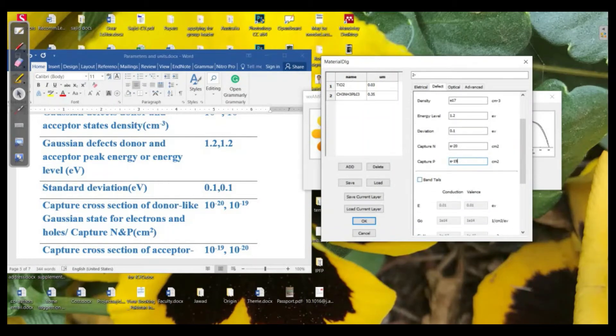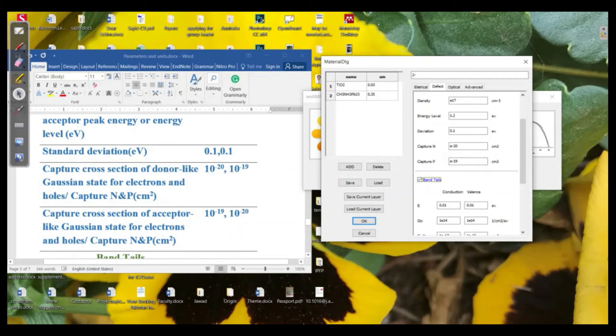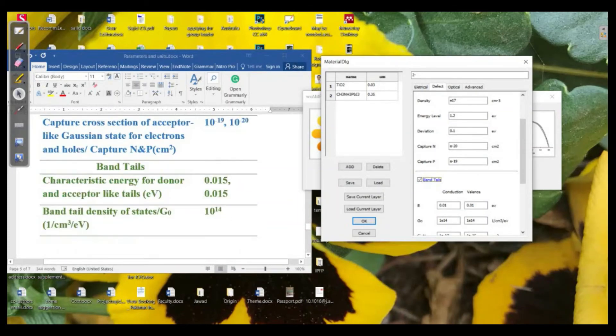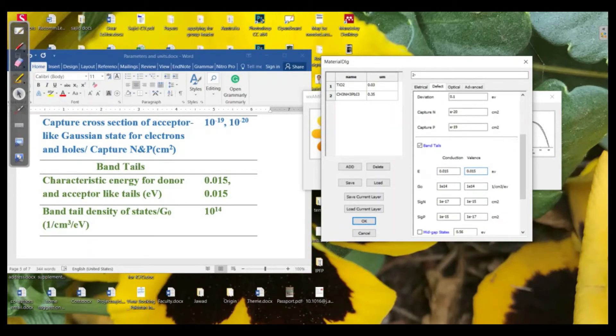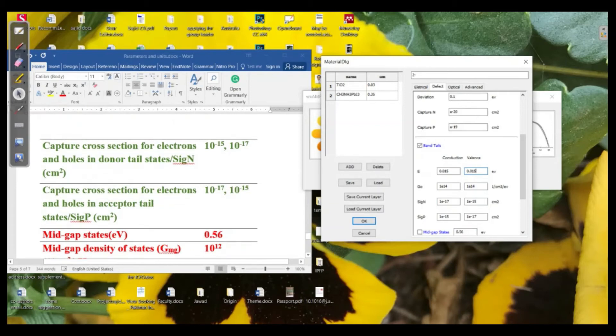Then we need to define the band tails for these defect states. For the perovskite band tail states, the characteristic energy is 0.015 eV in both cases. The band tail density of states, G0, is 10¹⁴, and the capture cross-sections for holes and electrons vary accordingly — this will be 10⁻¹⁵ and this will be 10⁻¹⁷, and similarly the reverse: 10⁻¹⁷ to 10⁻¹⁵.